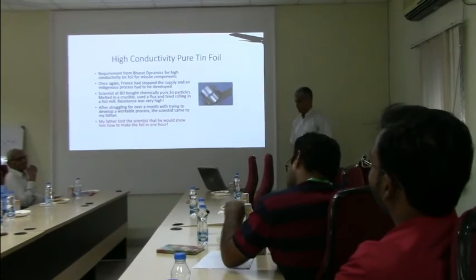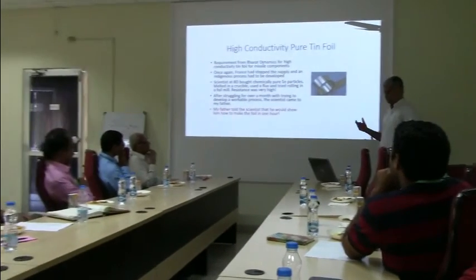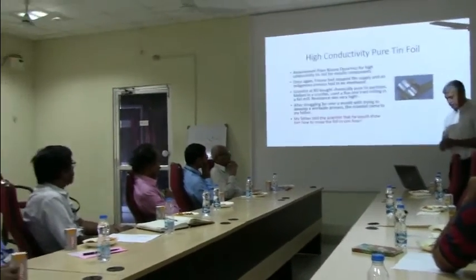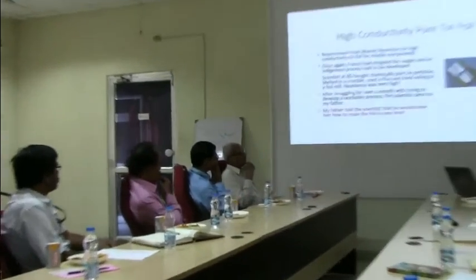So my father told him to bring a Pyrex glass tube, put all the tin pellets into it, evacuate the tube and seal it at one end, then show it to a flame and melt it. Tin melting is 230 degrees. So when it solidifies, any cavities that are there, you can basically roll it without much difficulty. Then break the glass tube, roll the pellet in a foil rolling mill, and measure the electrical conductivity. It became very easy to roll. And because there was no solid contamination, the conductivity was better than the imported stuff.